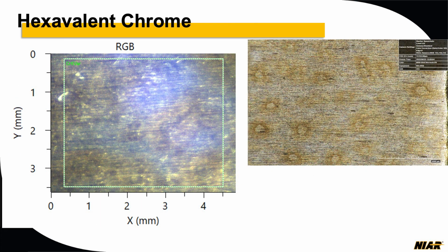The next sample is hexavalent chrome. One of the samples that we received, as you see on the right, this is a microscope image. So we have spots, and there's a non-uniform distribution of the chrome. One spot has a higher concentration. Just by visually looking at it, you see a yellowish spot, and in one area you don't see anything. So the question was, do we have a chrome uniform deposition on the metal pretreatment or not?